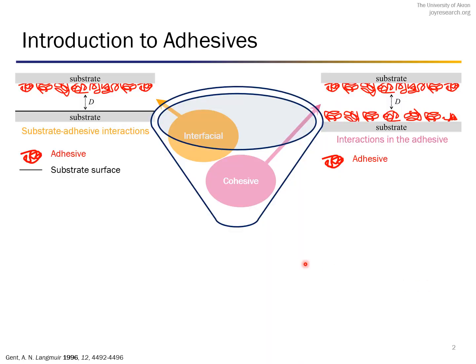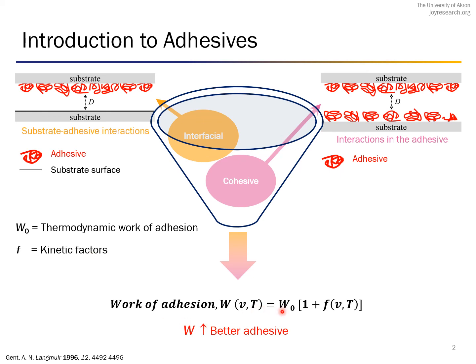Here I will introduce two concepts of adhesive science. So the first one is the interfacial part. The interfacial interactions means the interaction between the polymer and the substrate, which you can call the thermodynamic work of adhesion. Second is the cohesive strength, which is the interaction within the polymer, which is a kinetic factor. If you want to make an adhesive which sticks better, you need to optimize both these components, the thermodynamic and the kinetic factors.